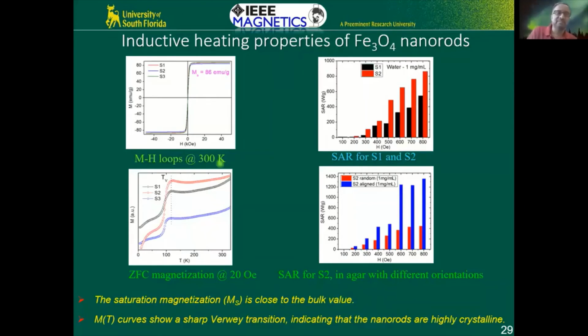For example, if you look at these nanorods, the saturation magnetization is 86 emu per gram. Bulk iron oxide is 92. We're almost there. We can almost get saturation magnetization close to that of bulk magnetite. And this is done through very careful chemistry and fine tuning the synthesis conditions. Another quality check in magnetite, besides high resolution TEM to find out the crystallinity, is this.